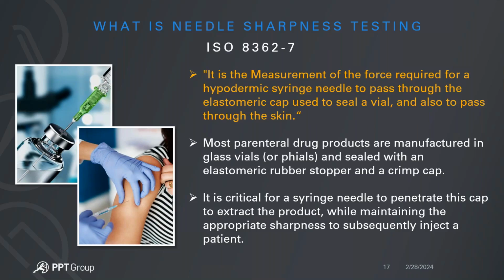So when we perform this particular test, usually we'll do a sharpness test where we'll either have an actual product that simulates that cap, the rubber, and also another product that simulates the skin. Interestingly, there are stores that actually sell simulated skin for nursing students in practicing their sutures and so on. So what we do, again, using a typical motorized tester, is attach the syringe needle, come down, penetrate the bottle, and measure the force resistance. In this case, a lower value indicates a sharper needle, whereas a higher value indicates a not so sharp or a dull needle, because then you get more force resistance that is necessary.